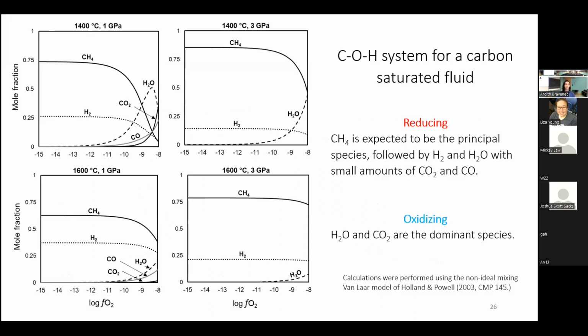And then I mentioned carbon before. That was purely for system OH. We can consider the opposite end member in a carbon saturated system. And again, there are fantastic equations of state that we can use to do this. So here you can see for different pressures, 1 and 3 GPa, in a reducing system, you expect methane to actually be the principal carbon species and to be the largest proportion of hydrogen as well. Whereas if you have a more oxidizing system, you might expect to have solely water and CO2.